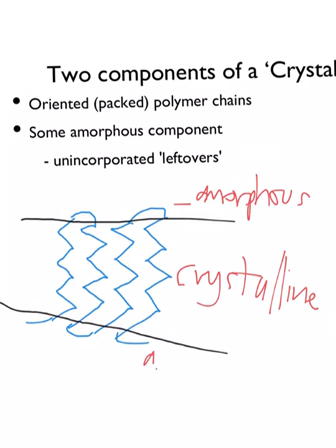So you cannot make those polymer chains bend and have them be crystalline at the same time. Hopefully that makes sense. We have to have puzzle pieces that fit into each other. These guys out here that are doing all this bending and looping back in, it's just not happening. All right, so even if you could nucleate the crystal the size of this table, which would be a phenomenal thing to do, one single crystal the size of this table, it would still not be 100% crystalline. Why? Because it's got this stuff out here. No matter how perfectly you do it, you're always going to have amorphous content. So at the bare minimum, you always have that. Okay? Hopefully that seems clear.